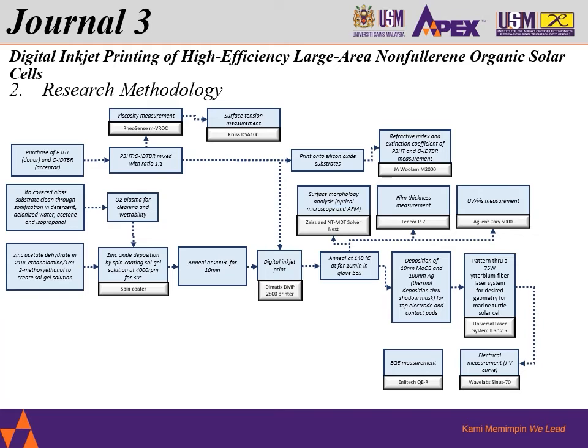After it was annealed, this is basically the active area. On the active area, some measurements and analysis were done: the surface morphological analysis, the film thickness measurement, as well as the UV-visible measurement. Then this was taken forward to finish the final device of OSC. Over here we deposit the MoO3 and silver using thermal deposition, and then some patterns were laser-patterned to achieve the desired geometry on top of the device.